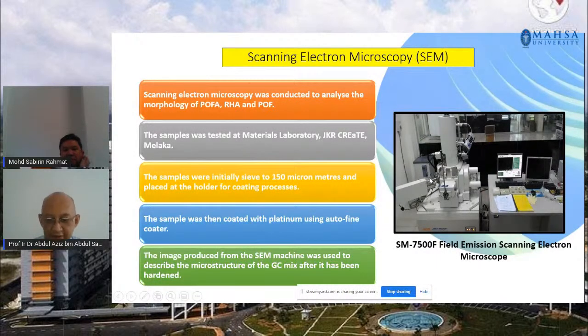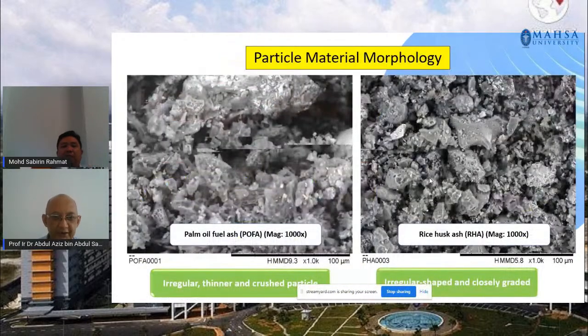So we did a study by using their machine, and this is what we obtained. The morphology for POFA and RHA, as you can see from these two pictures, POFA shows a bit more flaky and a more irregular size distribution, and a bit more chunkier in terms of size.